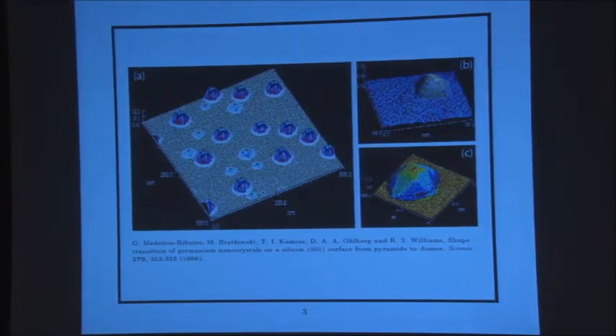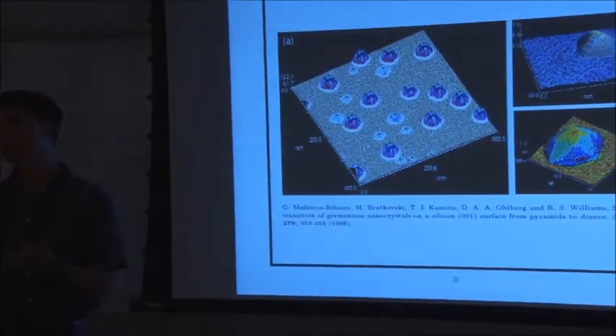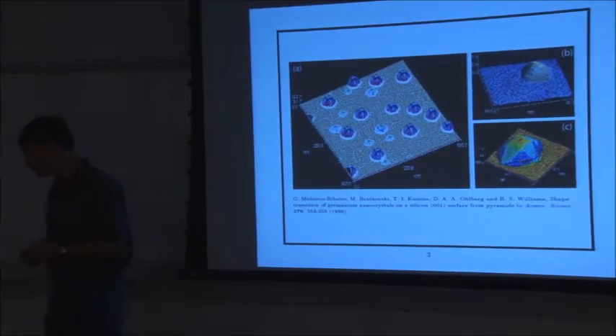This is an example of heteroepitaxial growth — an actual picture of germanium being deposited on silicon. Germanium and silicon are chemically quite similar, with two slight differences. The surface energy of germanium is slightly less than that of silicon, and germanium atoms have a slightly larger lattice spacing. So if you put a layer of germanium on silicon, it will strain the surface. The germanium is trying to spread out on top of the silicon wafer but can't, so it gets strained. The surface energy is enough to keep that layer flat — that's called a wetting layer.